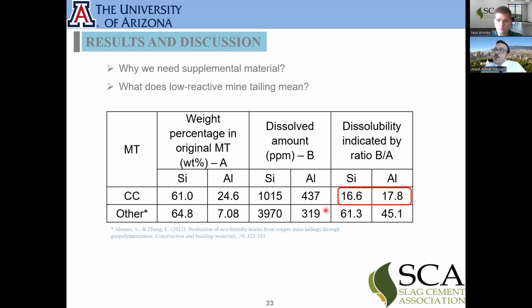If you have a huge amount of silica and alumina dissolving from the raw material, that means you are able to produce amorphous material. But otherwise, if your mine tailings is very crystalline, you're not going to be able to get enough silica and alumina from the tailing dams, and you're not going to be able to produce polymer networks, which we call geopolymer. So to help with this, we said, okay, we can use some kind of active waste material. And that's how we used slag material, which helped us in this study.